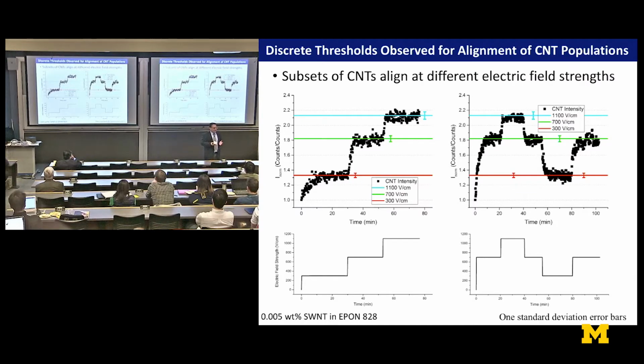I said, wait a second, you know, I understand mechanics, I understand diffusion. You put a different gradient on it, it should just happen faster. It shouldn't get to a different end state. Wesley stuck to his guns and actually was able to prove that this was due to the length distribution of the carbon nanotubes, because the driving force and the torque depends on length, and in this case, so does the polarizability. This is due to different populations based on length of the tubes aligning.